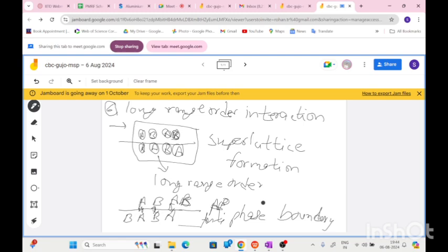If the width of the antiphase boundary is high, then the energy of this long range superlattice formation will be less. The stress tau naught is gamma divided by the width of the APB, where gamma is the antiphase boundary energy and this is the width. As the width increases, the energy will decrease, and if the width is less, the energy of the antiphase boundary will be high. If energy is high, higher stress will be required to move the dislocation further through the superlattice formed.